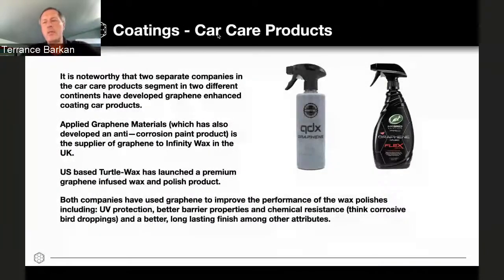I mentioned Turtle Wax, and I have that product at home. Two different car companies, two different continents, both came up with a similar solution independent of each other, which tells me that graphene works on its own merits. It's not just a marketing gimmick. And nanoceramics are really popular for barrier properties right now. And graphene is seen as being superior in performance to nanoceramics, giving better barrier properties, and it also blocks UV rays. And depending on the type of graphene you have, it is transparent, at least 98.2% in the single layer kind. So that's another example.